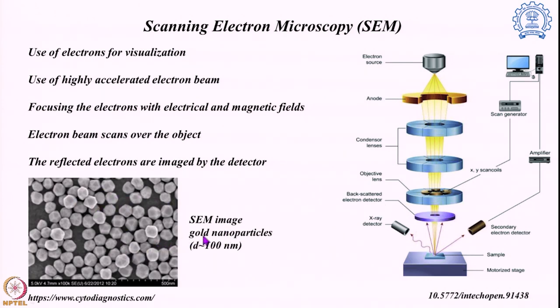So over there I am showing you an SEM image which shows gold nanoparticles with 100 nanometers of diameter. So each of them is 100 nanometers in diameter. So obviously you can see the scanning electron microscope, although it gives us a very nice picture of all around the system, the resolution of the system is not as good as TEM. In TEM we can easily go below the nanometer level, whereas in SEM we can go to almost the 10 to 100 nanometer region. That is where it acts better. So that is the difference between SEM and TEM.